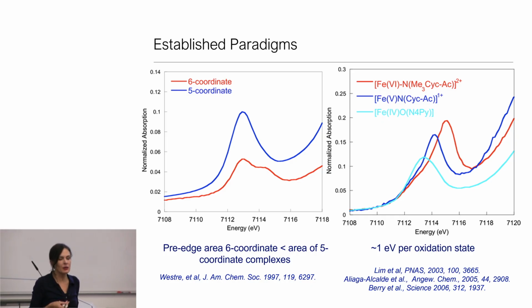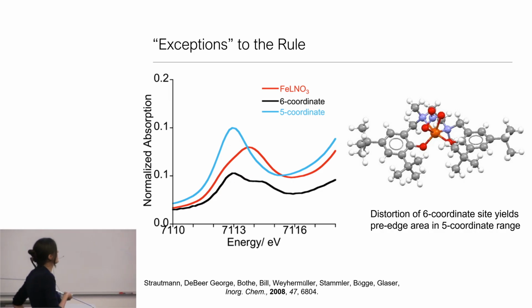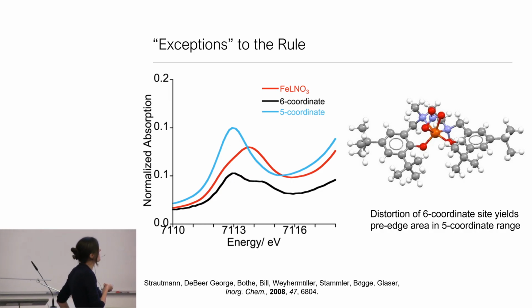But one thing I want you to always be aware of is there's an exception to every rule, right? And we always have to be careful. This sounds like a good rule to find out coordination number or oxidation state, but let me just show you some clear exceptions to this. This is a complex where we have a small molecule crystal structure. We absolutely know that it's 6-coordinate. But if we just use the pre-edge intensity or area of this red line, we might assign it as 5-coordinate. But when we look at the crystal structure, we can easily understand that while it's 6-coordinate, it is rotated from octahedral, right? And so once we have distortions, we have other mechanisms for intensity.